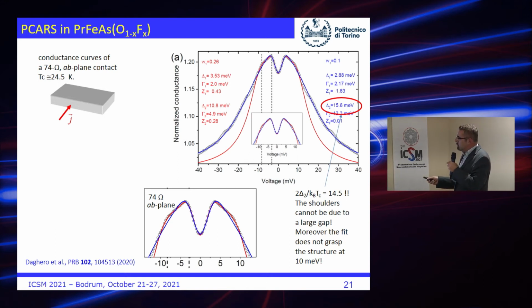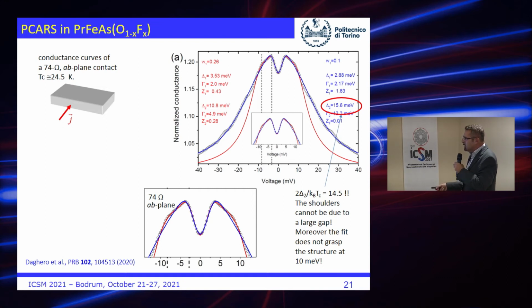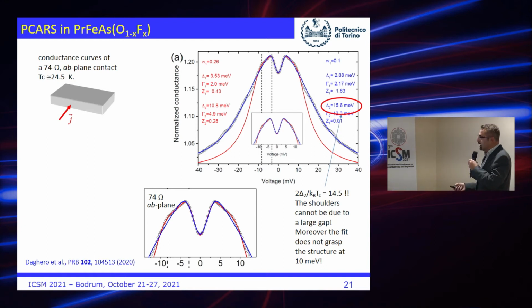But if you zoom here, it turns out that the blue curve is unable to grasp this change of slope, which is instead important because this occurs at low energy and this is likely to be a gap. So if you want to fit these two parts, and if you don't want to use 3 gaps, because 3 gaps means a lot of parameters, so 2 gaps are more than enough, you are forced to leave these parts out. So these are the 2 gaps, and these are again electron boson interaction structures.